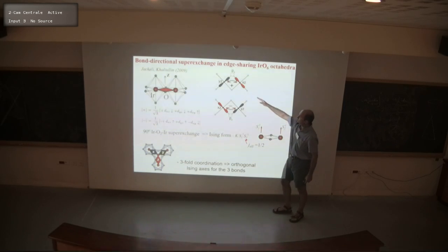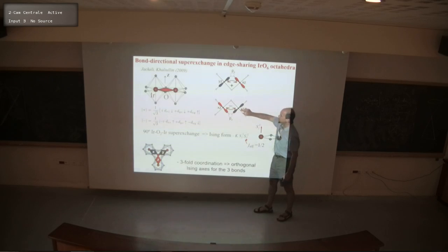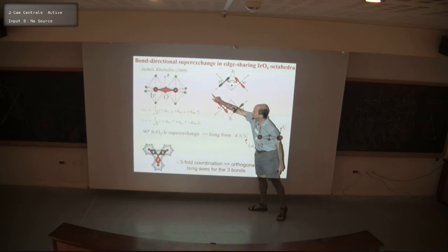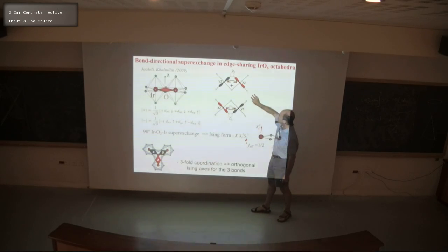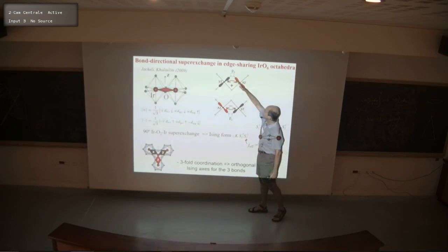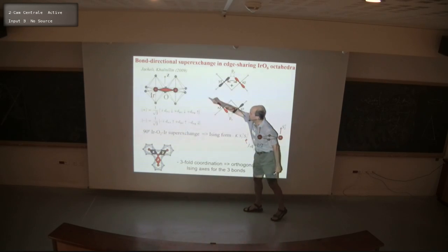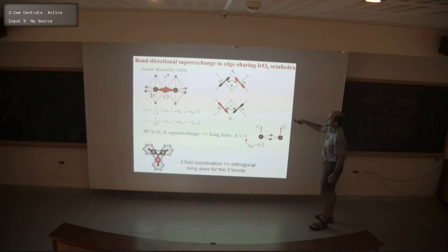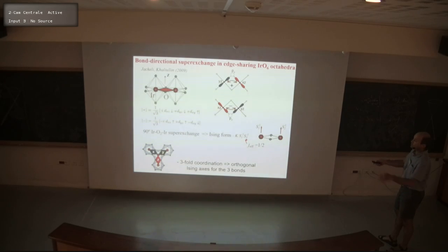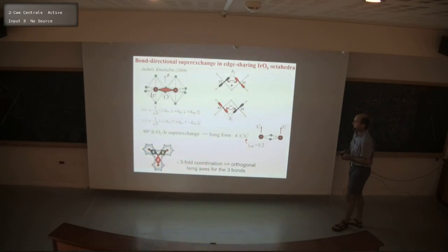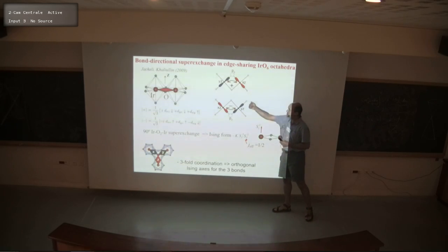For example, the only active orbitals are these orbitals that are orthogonal to the plane of the iridium-oxygen. So this is one iridium, that's one oxygen, that's the other iridium, that's the other oxygen. The hopping from here to there has to occur here through the xz orbital and here through the yz orbital. So the same spin state has to hop. There's a quantum destructive interference between these two paths, and this leads to a cancellation of the exchange to first order in the hopping. So the Heisenberg superexchange cancels in this configuration, and at higher order, the next term that's allowed is an Ising interaction between the components perpendicular to the square plane of the bond.